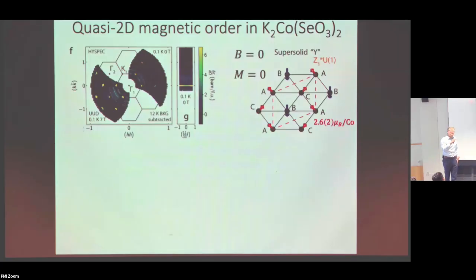And this, for me, was a bit surprising, because if I take 3 spins, and I'm going to have Ising-like variables, they can be up or down. I can really just do 2 up and 1 down. There'll always be some magnetization kind of left behind. But what we're finding is that even though I develop long-range correlations, I'm completely able to avoid any regions that have finite magnetization. Those are really extinguished from the structure.